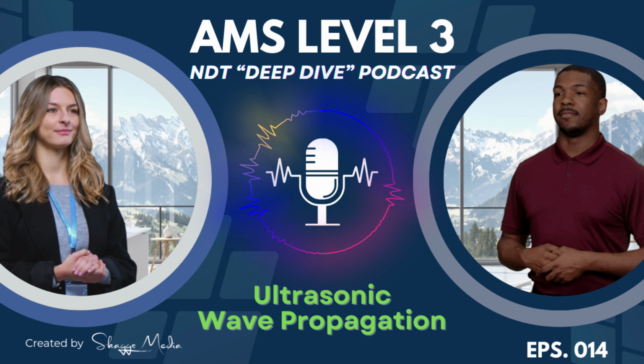Okay, so moving on. Whether we're dealing with longitudinal or transverse waves, isotropic or anisotropic materials, a huge part of UT is figuring out what happens when that wave hits something, a boundary, a flaw, a discontinuity. Right, and one factor is just the size of that something compared to the wavelength we're using. Exactly. If the discontinuity, say, a big crack face or a large void, is large compared to the wavelength of the sound hitting it, you get a nice clean reflection, almost like a mirror. The angle of reflection equals the angle of incidence, which makes the return signal predictable and strong.